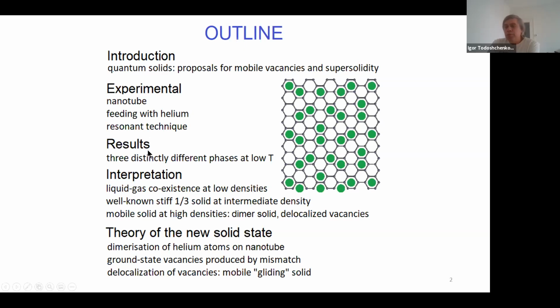Then I will explain the results which we have obtained. Basically, the main result is that we see three distinctly different phases at low temperatures, one of which is completely new and was never observed. I will give an interpretation of these phases. At low densities, at low coverages, we have liquid-gas coexistence as usual in 3D. At elevated densities, we enter the 1/3 solid, which is well established. This is the stiffest phase on the carbon nanotube. But when we increase the density even further, the stiffness of the solid drops, and we see something like a mobile solid, which is soft, at densities higher than this stiff one.